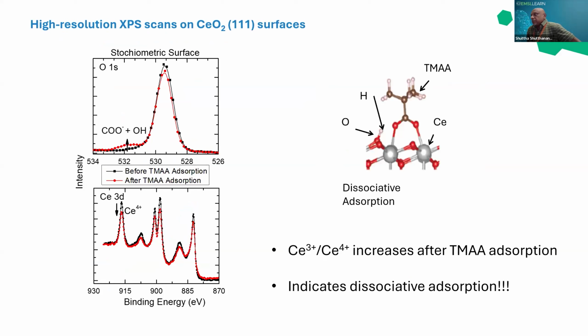Next slide, please. So here I'm showing the oxygen 1s and the cerium 3d spectrum. Again, you can see that the black one is the bare surface and the red one is the adsorbed surface. You can clearly see there is a peak coming. We have the C double bond OH corresponding. And then if you look at the cerium 3d spectrum, it also reduced a little bit. And then you can see there is a small shoulder coming on the lower binding energy side. So that means there is some cerium 3 plus forming in the presence of this carboxylic acid. So that is happening because some of the oxygens are transferring to the carboxylic acid group.